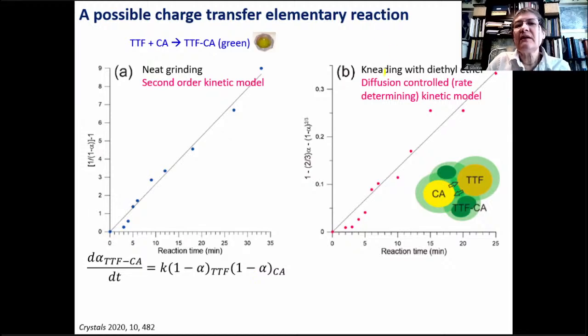So using diethyl ether for forming pastes, or kneading, we found a different kinetic model of the diffusion control type. That would be the diffusion of the reactants toward encounters, forming the product across layers of product, which could be the process that is determining the rate of the reaction under those conditions.